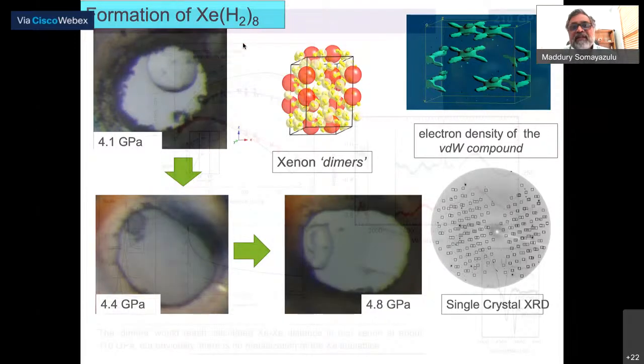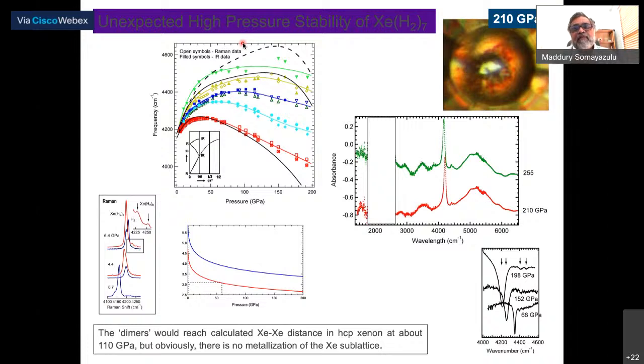But what is the intriguing part of it? The intriguing part is that, firstly, as you increase the pressure, the hydrogen-hydrogen vibron frequency fell, and that seemed to imply that xenon is beginning to tune the hydrogen-hydrogen interactions, which is what we want, because that is the driving force of trying to make molecular metallic hydrogen. But on the other hand, what we found is that there is an unexpected stability. The highest pressure we went up to was about 260 GPa, 2.6 megabars.